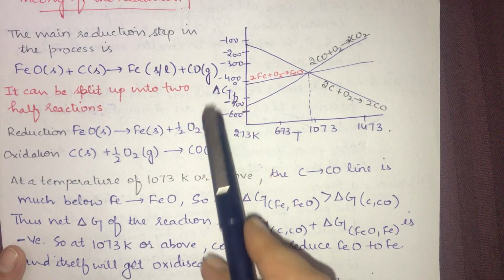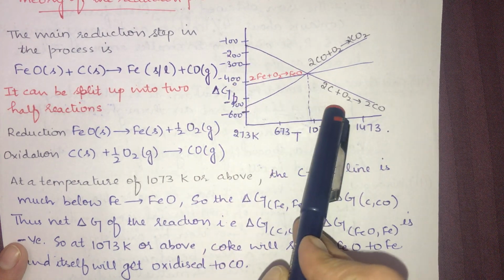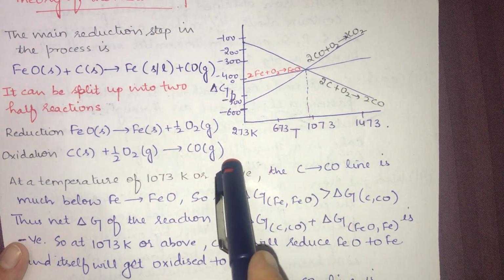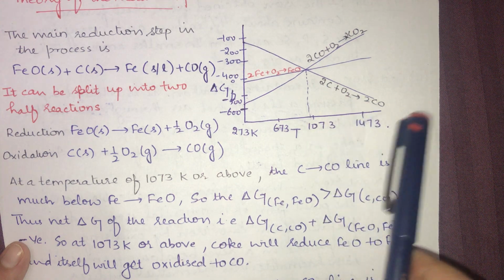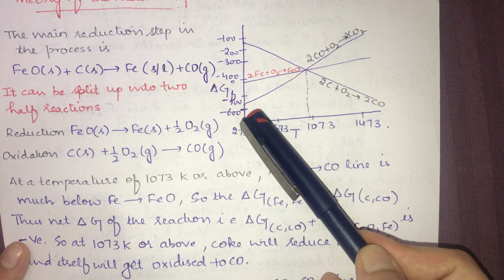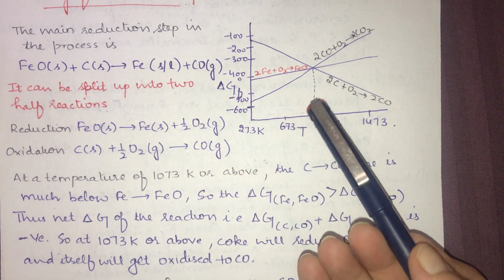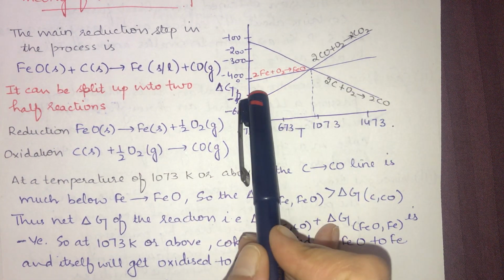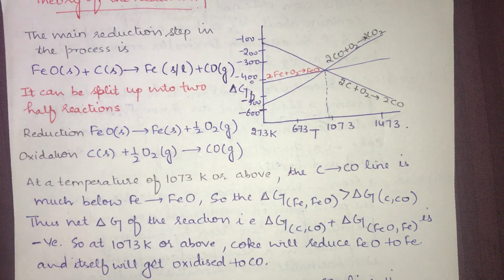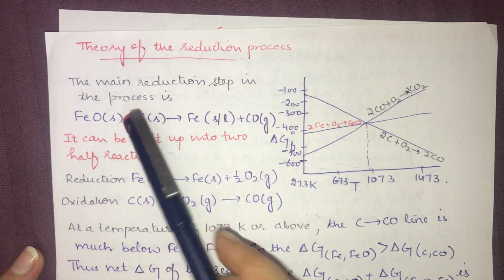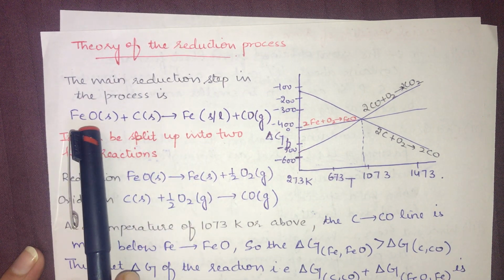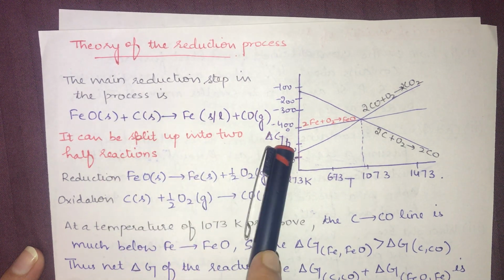Now what is this whole concept of the reducing agent? For that we need to look at the Ellingham diagram, right? If you see, carbon initially, below 1073 Kelvin, at lower temperature, the carbon line is above. So that means at low temperature carbon cannot act as a reducing agent. At lower temperature the carbon monoxide line is below. The line that is lower can reduce that particular oxide. So below 1073 Kelvin, CO will act as a reducing agent for FeO, and above 1073 Kelvin, carbon will act as the reducing agent for FeO. So the whole process carried out is in accordance with the Ellingham diagram. The main reduction step of the process is that iron oxide is reduced by carbon to Fe and carbon monoxide is formed.